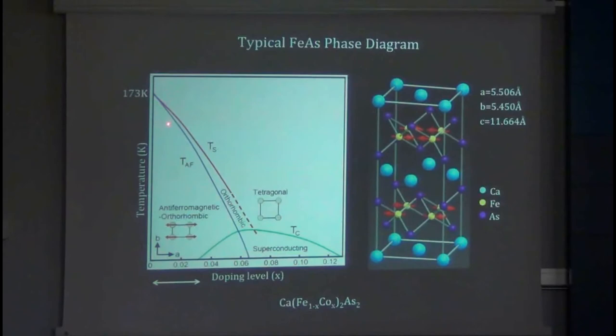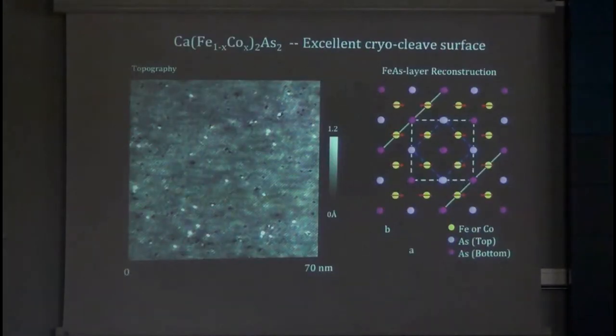Phase diagrams of these compounds have many common characteristics. The parent state is an antiferromagnet, but it's a metal, not an insulator. You can suppress the antiferromagnetism by changing the carrier density, and as the antiferromagnetism goes to zero, the superconductivity appears. So we first started working with Paul Canfield to study calcium 122, which I saw today is also being studied here quite beautifully at UAM. So we did our experiments in this doping range here in the parent state from which the superconductivity emerges.